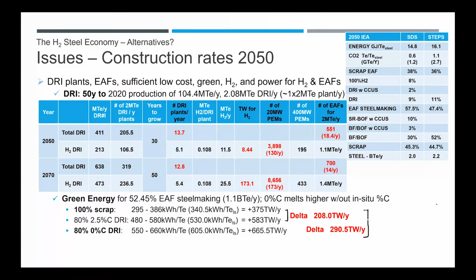In terms of the EAFs, you're looking at 551 new 2 million ton a year EAFs, or 700 when you get to 2070. And then if we look at the green energy, this was a quick calculation and it's a bit on the low side in terms of kilowatt hours per ton of liquid steel. But basically, if you're going to use 80% zero carbon DRI in the arc furnace, you're going to look for an additional 290 terawatts. Next, please.